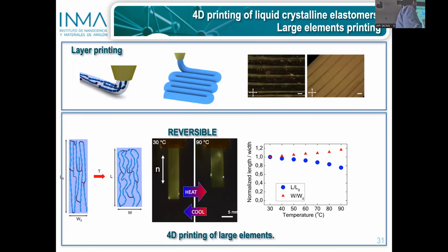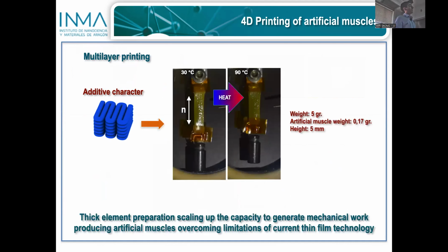We can get continuous layers of material by printing adjacent lines of material, and here you more clearly see that the stripe on heating contracts along the director, along the preferential orientation direction, and expands perpendicular to it, as you can see in the plot. Due to the additive character of the system, we can generate multiple layers, so we are not limited anymore to the thin layers that we have with the previous thin film technology. So we can go to thicker elements, and there we can do a substantial amount of work. Here you have an element that is able to rise a significant distance, comparable to the same order of magnitude of its own length, and lift an object that is many times its own weight.